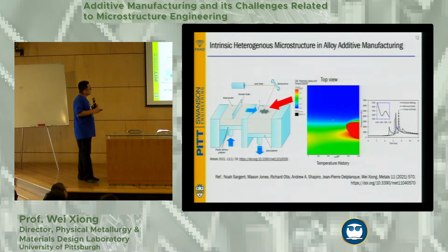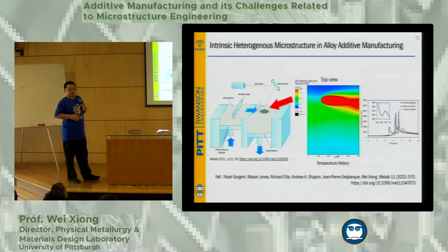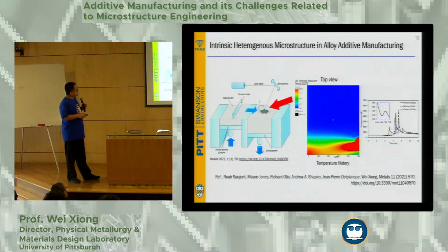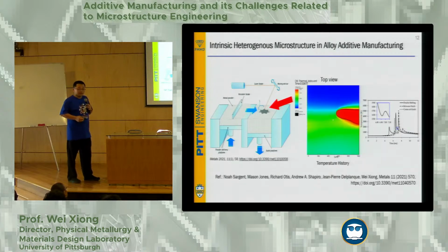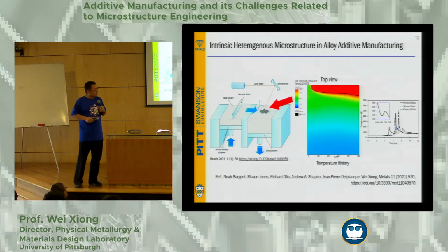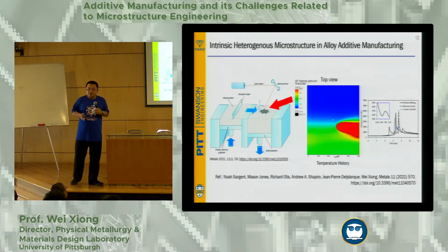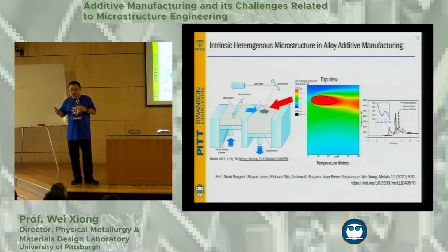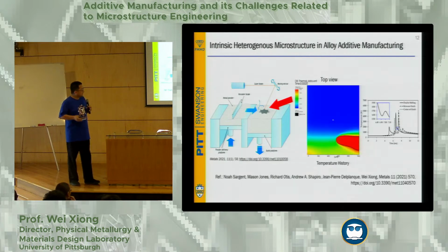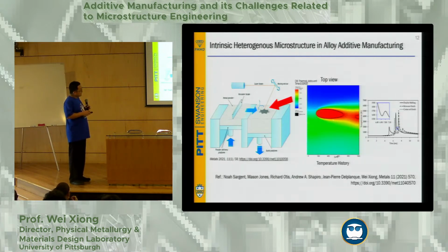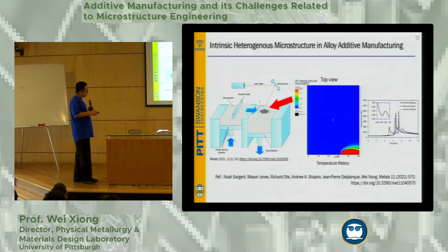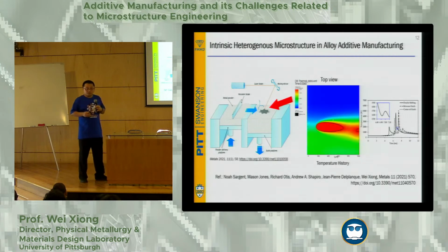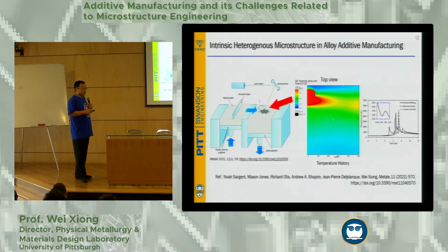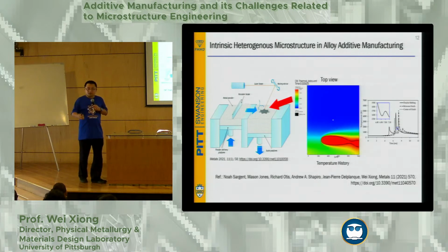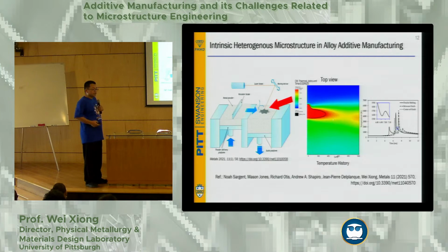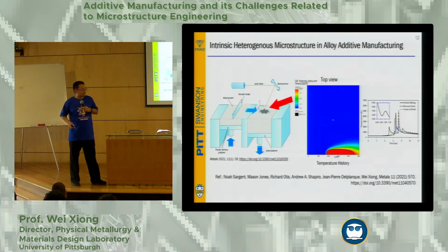So this is the one that we did simulation on and tried to understand. For those of you who are not quite familiar with this thermal history, it's actually very complicated because it's laser melting, depending on the heat source, of course. Some heat sources can introduce heating and cooling rates up to 10^6 K per second, all right? And of course, it depends on the material and the powder that you're going to use. Anyways, I don't think anyone so far can precisely measure all of these thermal gradients, or temperature gradients, at the moment. That is also bringing another challenge, where if you cannot measure it, it's very hard to improve and control. And a lot of things still focus on the heuristic design of this microstructure.